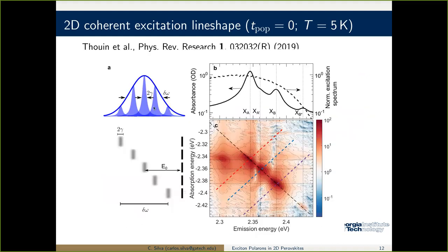This is the idea by which I can measure the homogeneous and inhomogeneous line width. The line shape of these two-dimensional spectra tells me that the dephasing is embedded both in the anti-diagonal as well as in the diagonal line shape. Because I understand the line shape, I know how to extract the dephasing from that line shape function. It's a combination of a Voigt profile in one direction versus a convolution or a product of a Gaussian with an error function in the other one, and basically I can pull out the dephasing, which represents a homogeneous broadening. I don't want to go through that. I just want to show you the results because I'm quickly running out of time.